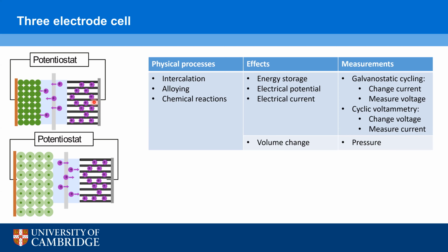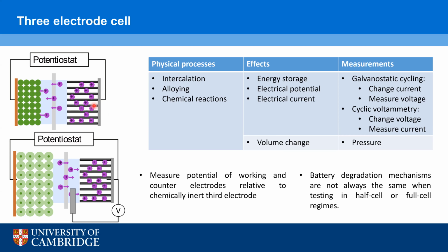So what we can do is use a 3-electrode cell by introducing a third reference electrode, which in a lithium-ion battery would be a lithium metal electrode. And then by measuring the potential difference between the anode and the reference electrode and the cathode and the reference electrode separately, we can then measure